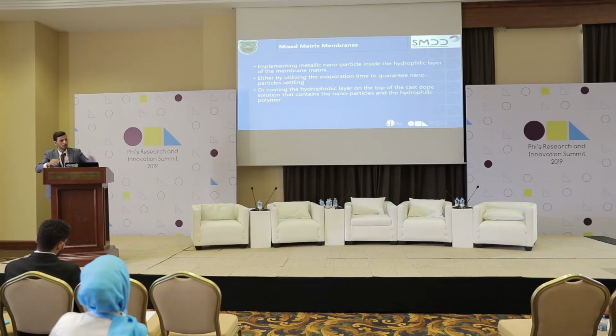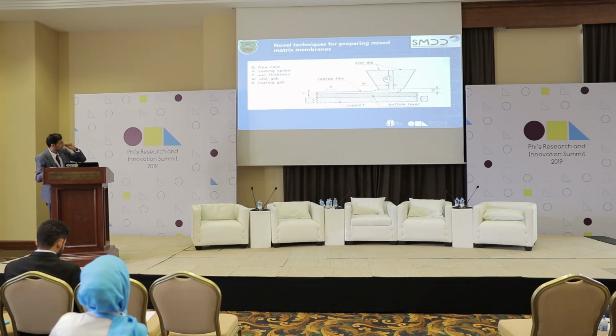But again, evaporation time is not an option in industry because the casting machine should be running at a capacity of 15 meters per minute without any stop. So you just can't stop. So we thought about another idea, which is coating of the hydrophobic layer on top of the hydrophilic layer. And we achieved this by designing this machine.